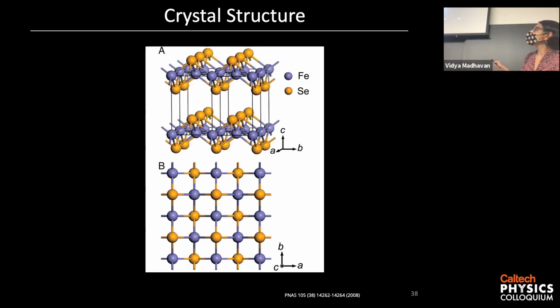And this is the top view. This view shows all the 3 layers of the FeSeTe plane. So you can see the top tellurium atoms, the middle iron atoms here in blue, and the tellurium atoms below. The important thing to notice here is that the tellurium atoms on top and the tellurium atoms underneath are actually shifted from each other by half a unit cell. And that means that when you look at this crystal, you realize that what you call the top tellurium atoms, you could actually take this layer and flip it over, and then these things would be on the top, but they would be shifted by half a unit cell.